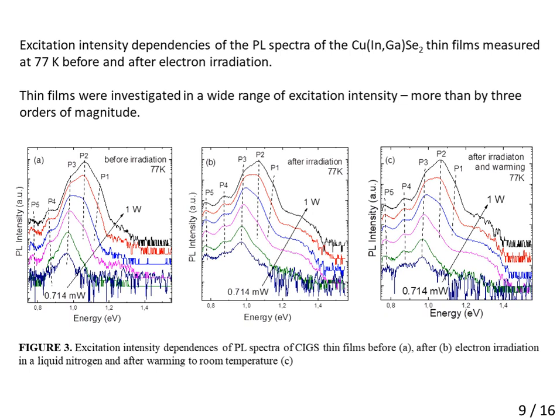Thin films were investigated in a wide range of excitation intensity, more than 3 orders of magnitude. It can be seen that with rising excitation intensity, not only the intensity of the photoluminescence bands changes, but also the energy of these bands. This is due to the specific recombination mechanism.